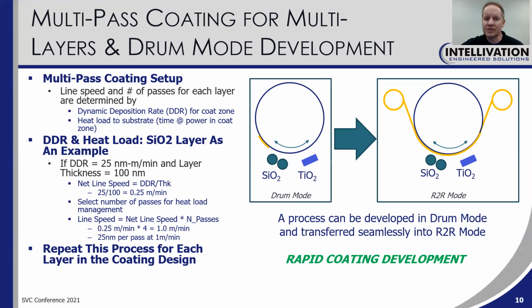We select the number of passes in order to manage the heat load. This is in a lot of cases just determined experimentally. Different substrates behave differently. And then we multiply that speed by the number of passes and run the material through the machine that number of times. And then we repeat that for each layer in the stack.